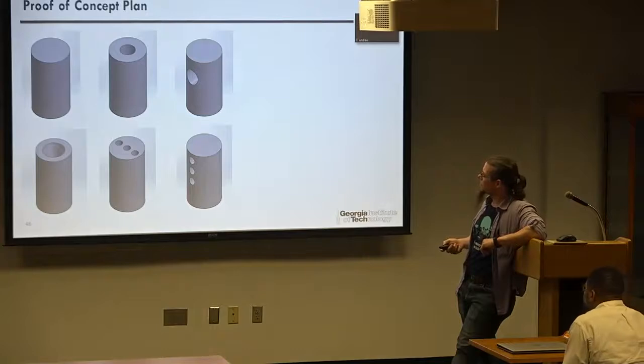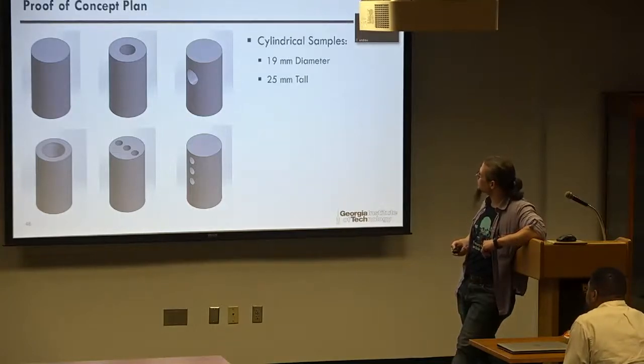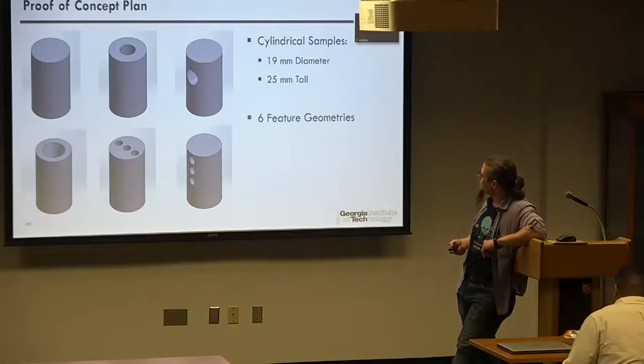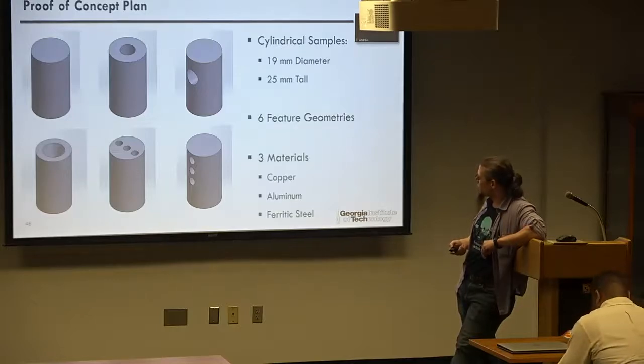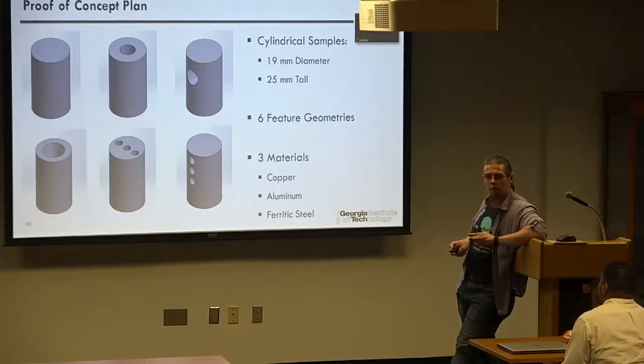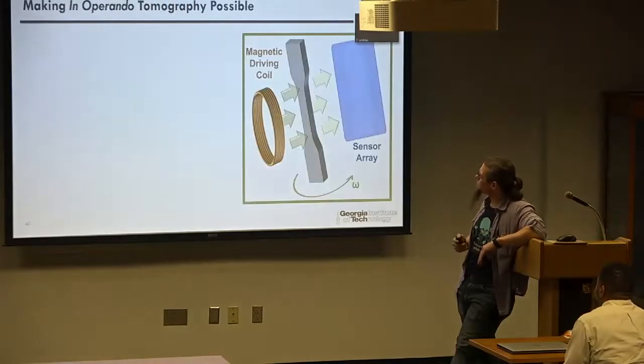Here's the samples that we have machined. They're 19 millimeter diameter cylinders, 25 millimeters tall, 6 different feature geometries, and we're working with copper, aluminum, and ferritic steel. So that gives us 2 different resistances for the materials that are non-ferritic, and then we have a ferritic steel to see what mayhem it wreaks.